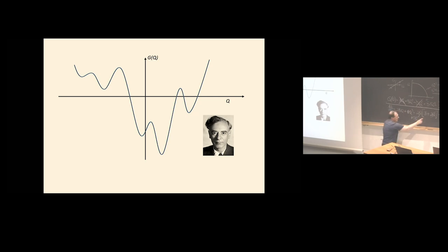The other solution is that if this entire thing in brackets is 0, we're going to end up with Q squared equaling minus B over 2D. So that's also a solution. So we already have two solutions, one of which we know by definition is the high symmetry, high temperature phase. That's quite a victory. And the other then must be the low temperature, low symmetry phase.